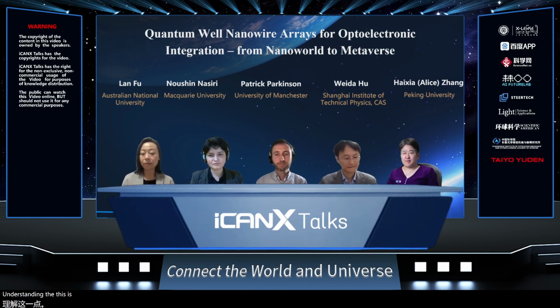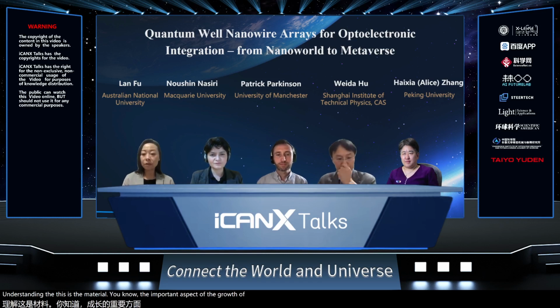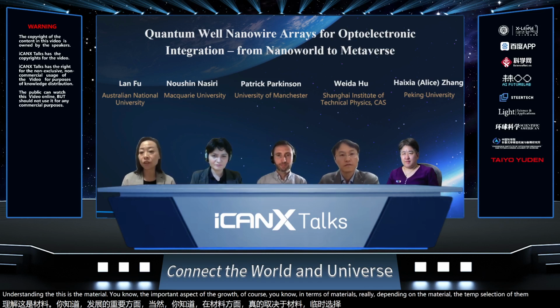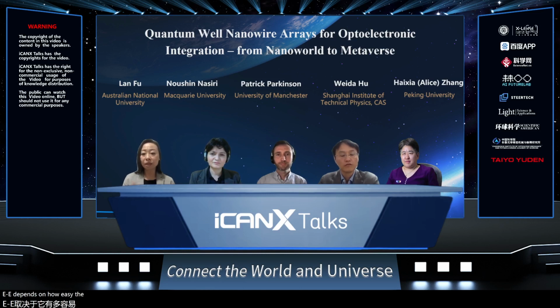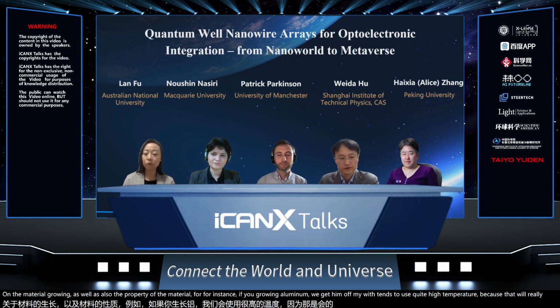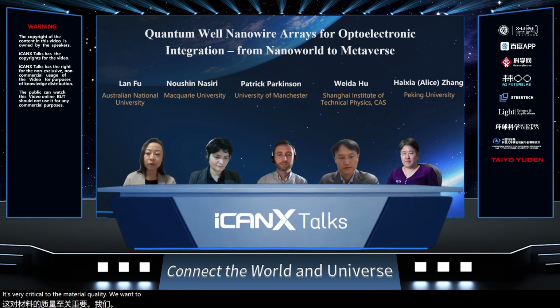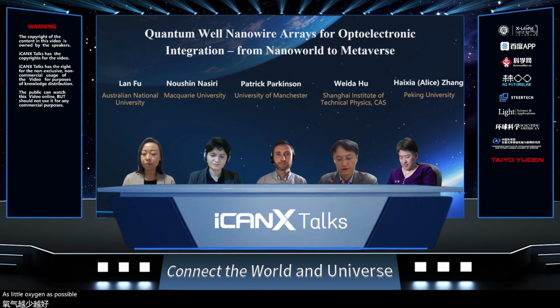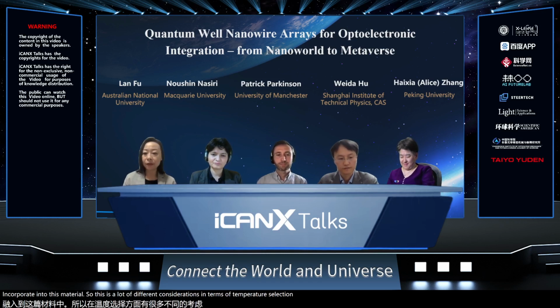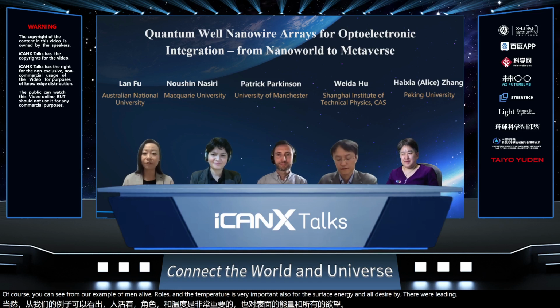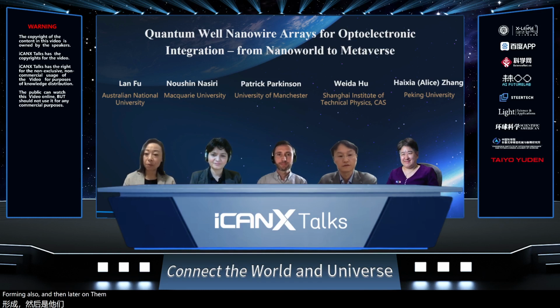So it's more about understanding the material and the important aspects of the growth. Of course, the selection of the temperature for the growth depends on the material. It depends on how easily the precursors crack into different atoms and all this. So that really depends on the material being grown, as well as the properties of the material. For instance, if you're growing aluminum gallium arsenide gallium arsenide, we tend to use quite high temperature because it's very critical to the material quality. We want as little oxygen as possible to be incorporated into the material. So there are a lot of different considerations in terms of temperature selection. Of course, you can see from our example of nanowire growth that temperature is also very important for the surface energy and all this, which leads to different facets forming, and later on the properties of the material as well.